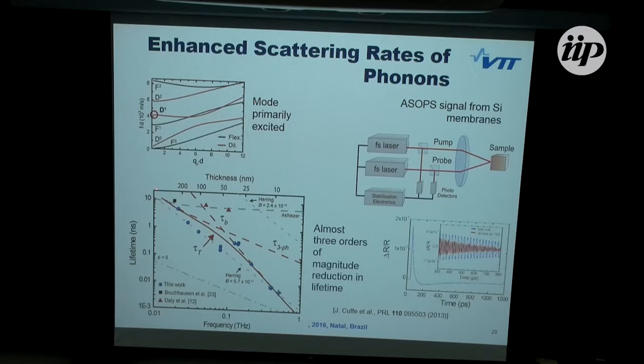Different thicknesses. So this is thickness, and because thickness decreases, the frequency of the phonons increases. These blue dots are the results. So there is normal scattering in thick samples, but then when the sample thickness goes down, boundary scattering or surface scattering sets in, and actually the effect is very strong. It has 3 orders of magnitude reduction in lifetime. By the way, the ASOPS signals look like this, and then from this decay, one can get this scattering time or lifetime.